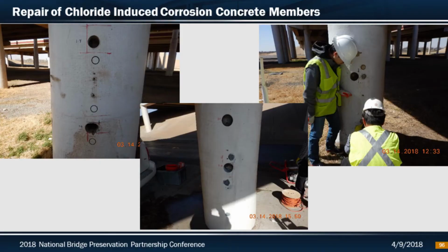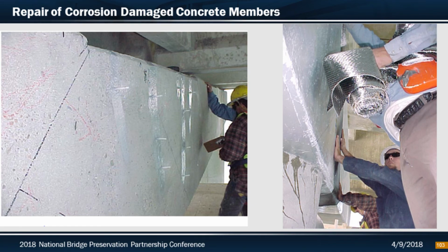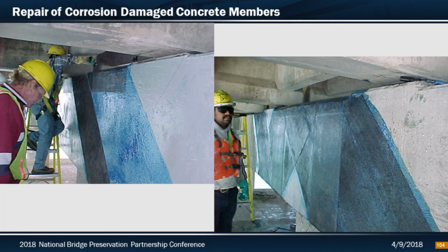This was down in the marine environments, probably due to an open joint, and poor consolidation on the bent cap at the time of construction. We ended up losing several stirrups due to the corrosion, a lot of deteriorated delaminated concrete. So it was utilized both vertical and 45-degree angle CFRP wrapping to increase the strengthening and repair the cap back to where it could be utilized. Also, galvanic anodes were added to protect for future corrosion. Cracks were injected. CFRP was installed per design in the 45-degree angles.